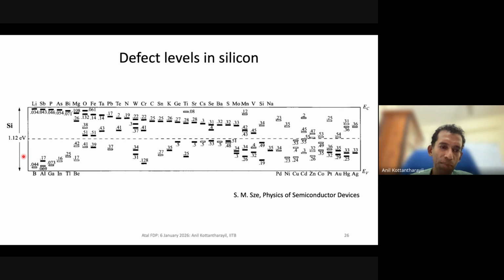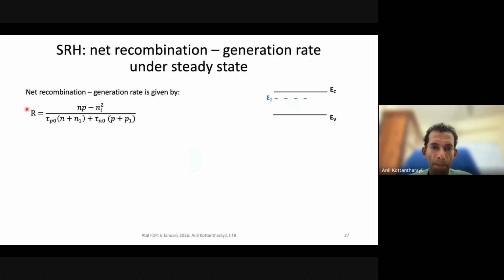So you can see this is the band gap of silicon, and if you have any of these impurities in the semiconductor, you can get these electronic states in the forbidden band gap of the silicon. So it's very, very important for us to make silicon material which is ultra pure. Silicon that is used for semiconductor and solar cell manufacturing has less than parts per billion or parts per trillion of impurities. So that's one of the big challenges. In fact, this is the purest man-made material which is widely used for industrial applications, right?